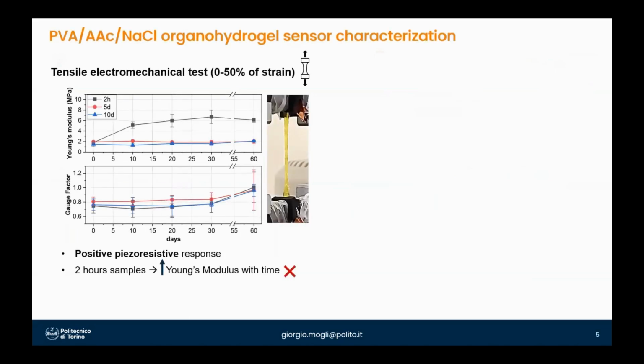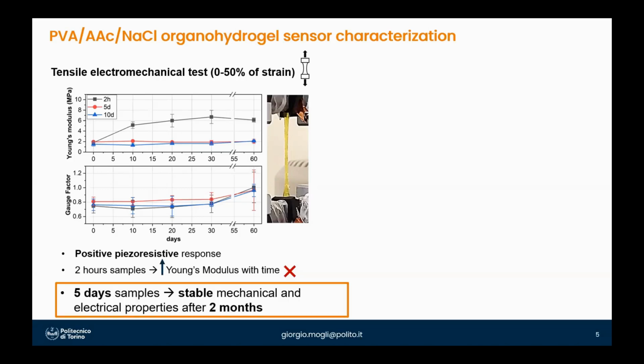Then, since this organohydrogel is thought as a strain sensor, tensile electromechanical tests were carried out, and the Young modulus and gauge factor in the first linear range of the response of the sensor were evaluated. As regards the Young modulus, as we can see, the 2-hour organohydrogels do not have a stable Young modulus, since their stiffness starts to increase after 10 days of testing, and so they were excluded from the study. On the other hand, the 2 other hydrogels taken into account show both mechanical and electrical stable properties along 2 months of study. So the 5-day samples were taken into account, since they take less time to build.